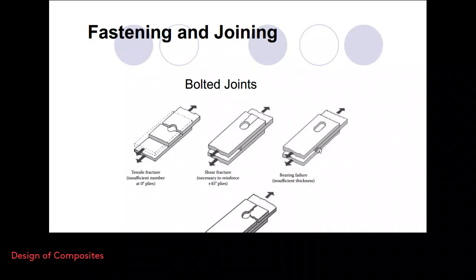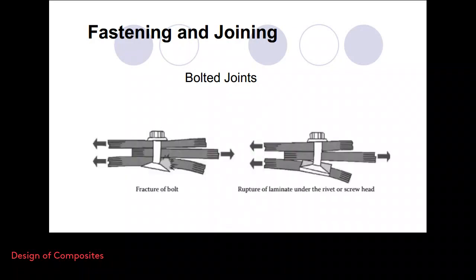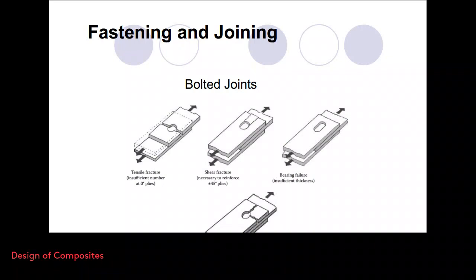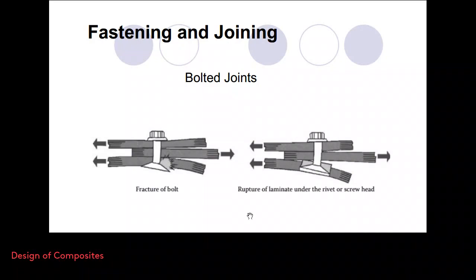Bearing failure. As you see, the hole is elongated somehow, which means that the fiber matrix delamination, matrix debonding, and in fact this means that the thickness has to be increased in this case, because the hole is not capable of carrying the applied load. And finally, both tensile and normal fracture, so the thickness is not sufficient in general for this type of design.